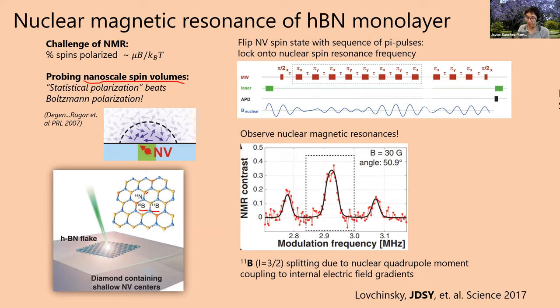So that's what was done in this experiment. We were not the first to measure an NMR signal with an NV center. We were just the first to try that with a 2D monolayer, in this case, hexagonal boron nitride. I'm not going to go into this too much. I just want to say that this has a lot of cool general quantum sensor stuff in it. We have a single NV center that we use, in an isotopically purified diamond.